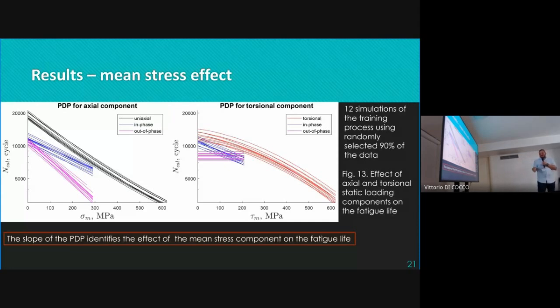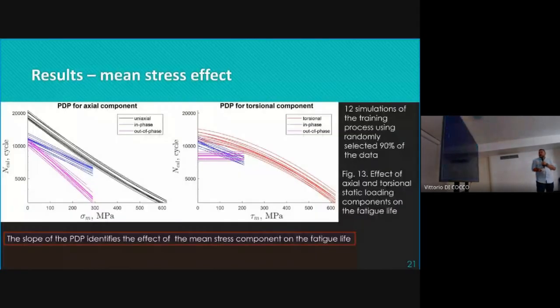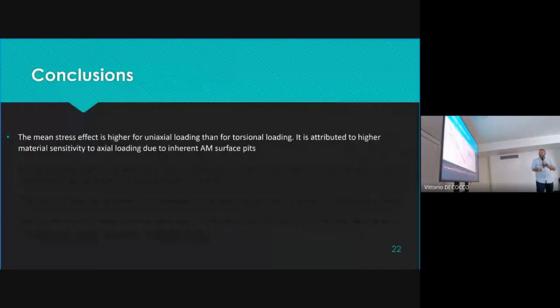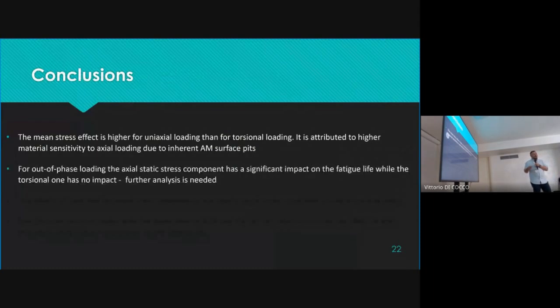So, going to the conclusions. I think I skipped. Okay. The mean stress effect is higher for uniaxial loadings than for torsional loadings. It is attributed to the higher sensitivity of the material to axial loadings due to surface pits. Under out-of-phase loading, the axial static stress component has a significant impact on the fatigue life, while the torsional one has absolutely no impact. We need to further analyze this one.